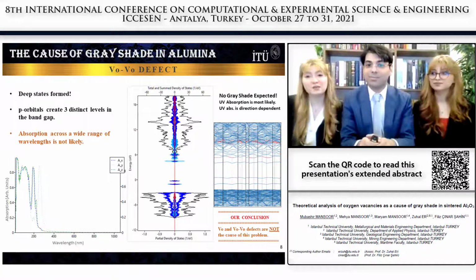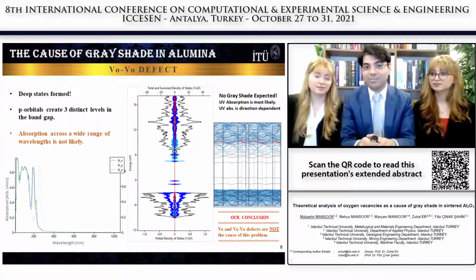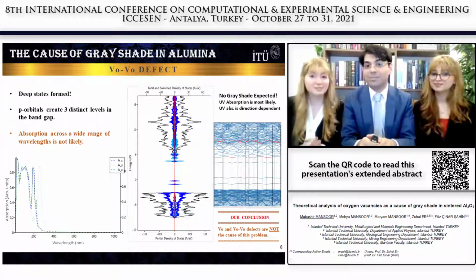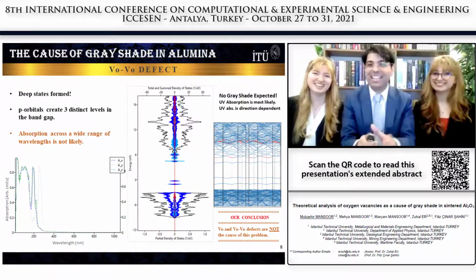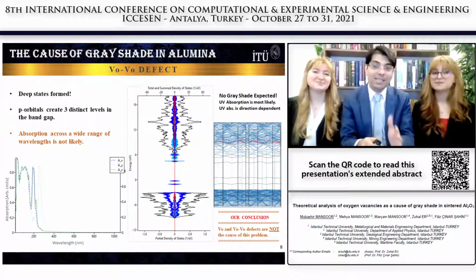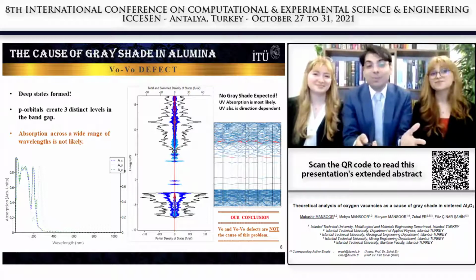So we can now safely say that oxygen vacancy and di-vacancy are not capable of creating a gray shade in alumina. And we can refute the oxygen vacancy theory based on this research. However, the question remains, if oxygen vacancy is not the cause here, what else could it be?